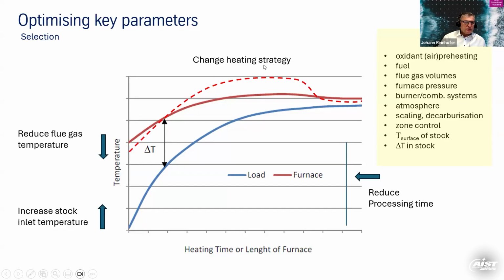You can change the heating strategy. You can go higher with the temperature in the heating zone, for example. What does it mean? You have higher temperatures in the stock, and so on, scaling, all sort of things. You can reduce the whole processing time by improving the heat transfer. What does it all mean? It has to be really carefully looked at. As I said, there's no one-fits-all solution. Every furnace is different in the end.